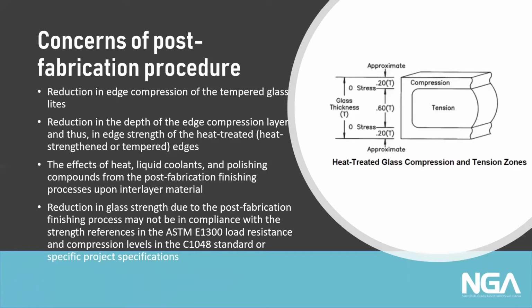The effects of certain things with regard to heat, cooling liquids, and polishing compounds also have an effect on glass. I've had some issues personally in my consulting business where I've had to go out and look at glass that was delaminating for various reasons, and some of it did point back to the fabrication and post-fabrication, which was done to give a nice smooth edge, but also some of the coolants and the heat that was done had some effects on the laminate in the sense that it caused some problems, both aesthetically and structurally.